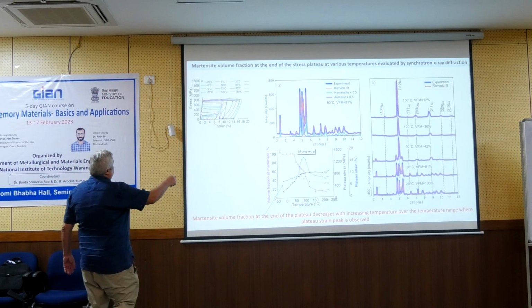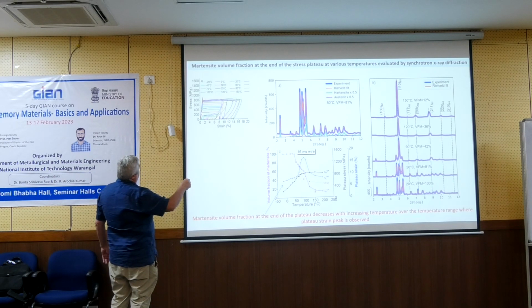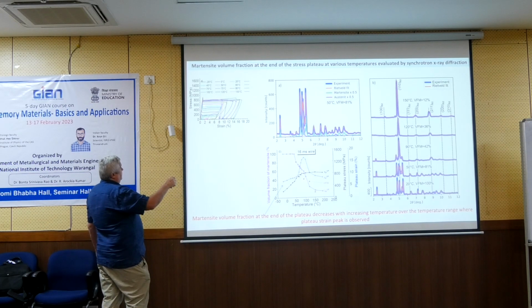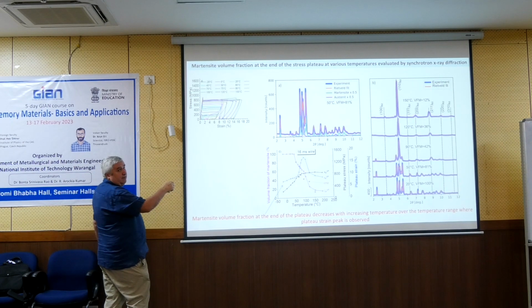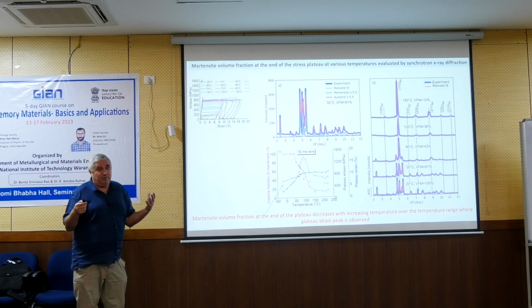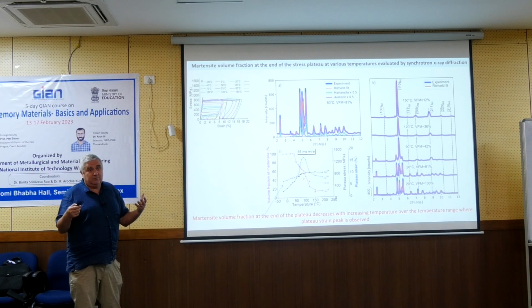Okay, what you said is the green. At room temperature, it's perfectly recovering. But now around magenta, which is like 50 degrees, there is still a plateau, but on the reverse, not everything recovers, which suggests that something must have happened during the loading or unloading. Probably during both, but as a result of this, you have non-recovered strain. And even if we heat it, we could recover only 0.5%, but still 2.5% remained. So somewhere during this loading, the plastic deformation was created.